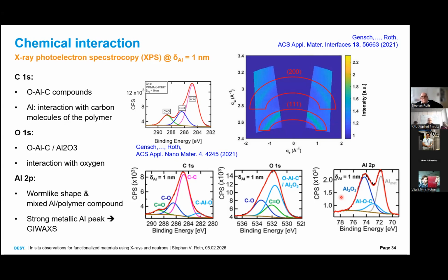Unfortunately not. What we do here is repeat the experiment in the lab of our Kiel collaborators, who have an identical sputter chamber with an XPS on top. We always prepare several samples of the same polymer film. We measure in situ, we prepare samples for AFM and SEM measurements, and then we go with the freshly prepared polymer film to Kiel, deposit the metal layer, and do the XPS. So it's not directly in situ, it's ex situ in that sense, but under the same conditions so that we can really compare it.